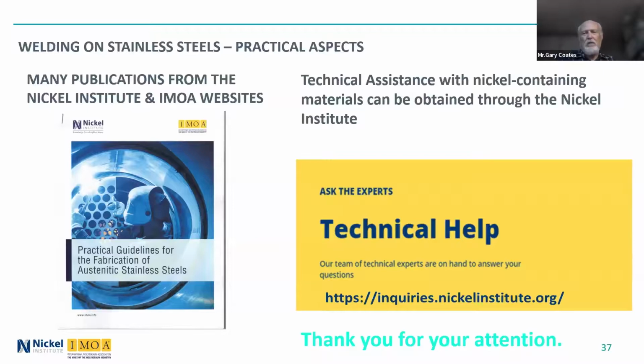And so when they're used at high temperature, if the carbon is not tied up as a niobium or titanium carbide, it will tie up with chromium, and that reduces the corrosion resistance. This is very important when you have hydrogen sulfide in a line, that when cooling down, the hydrogen sulfide will form polythionic acid. It's a chemical where hydrogen sulfide combines with water in an air environment, and it will crack these alloys.